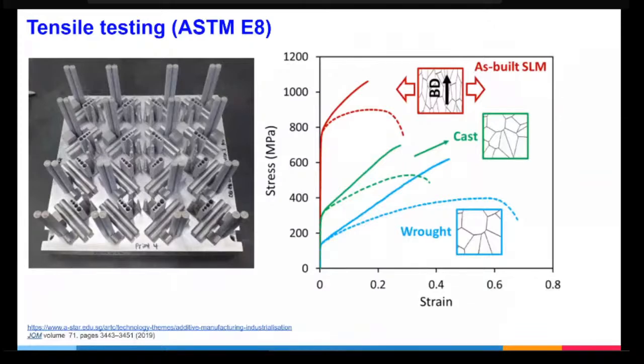Once the component is made, by a simple tension test you can find how the properties look. We should always remember that we should compare these components with the baseline, which is the wrought product. For example, this is the 3D printed component, and what is shown on the top right is the build direction. The testing is done by pulling perpendicular to the build direction. What is seen here is higher strength, but ductility is limited. We should always compare these properties with the baseline, which in this case is wrought, what is commonly available. You can quickly conclude that though the process has ended up with a higher strength, the ductility is compromised.